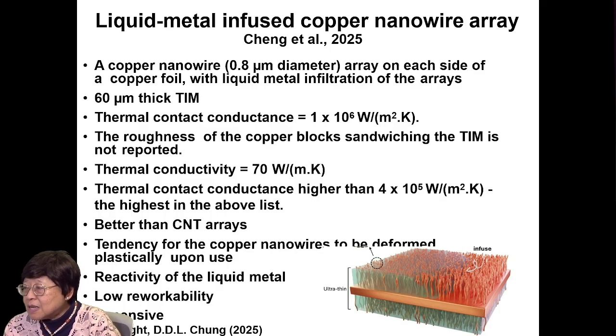The roughness of the copper blocks sandwiching the TIM is not reported. As I said, the roughness needs to be specified, otherwise you cannot compare apple with apple. But the roughness is not revealed in this paper. The thermal conductivity is very high since it's all metal, 70 watts per meter K, and the thermal contact conductance is higher than the value of 4 times 10 to the 5 watts per meter square K for the best material in my list just shown, and that best material is the nanoclay thermal paste. But again, the comparison might not be fair because the roughness is not revealed in this 2025 work by Cheng.